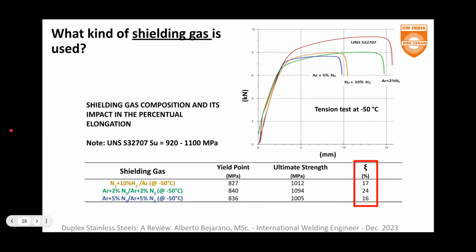Let's advance here. What kind of shielding gas is used? I recommend you to use 2% nitrogen, 98% argon, or in other terms, in some literature, catalogs or books, you find argon with 2% nitrogen, which means that the rest is argon. Here the red line is the base metal. And if you look, this argon 2% nitrogen has almost the same behavior, so it's the best option for us.